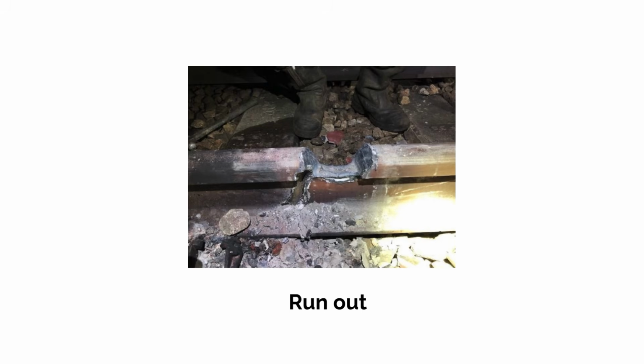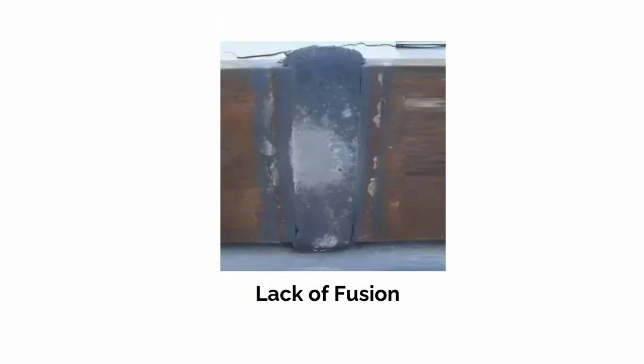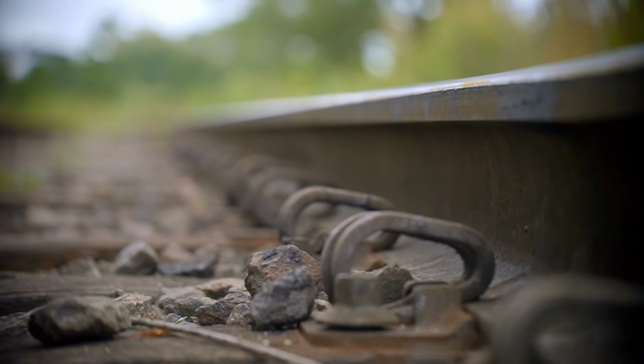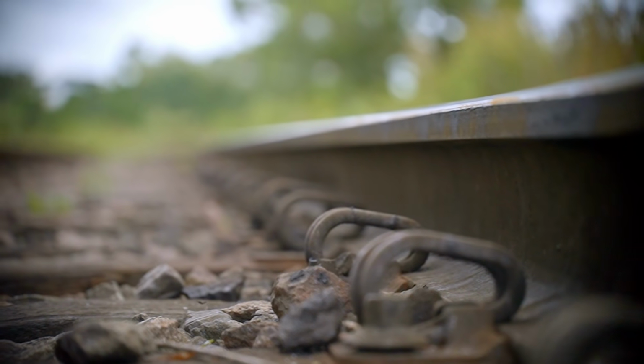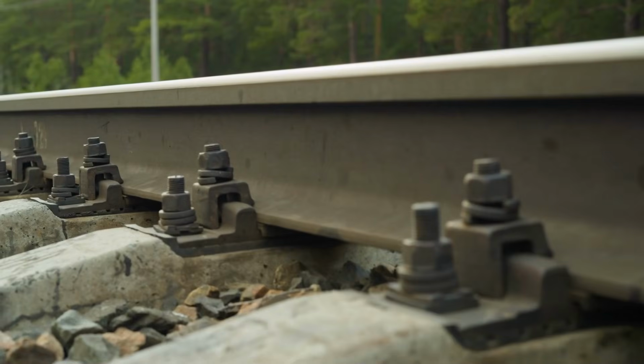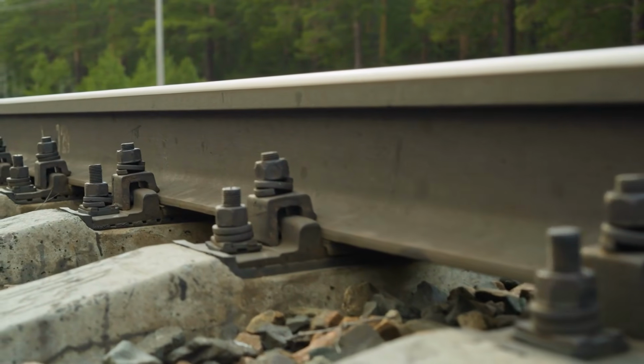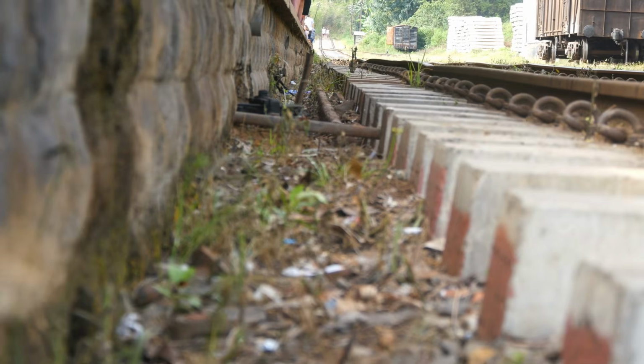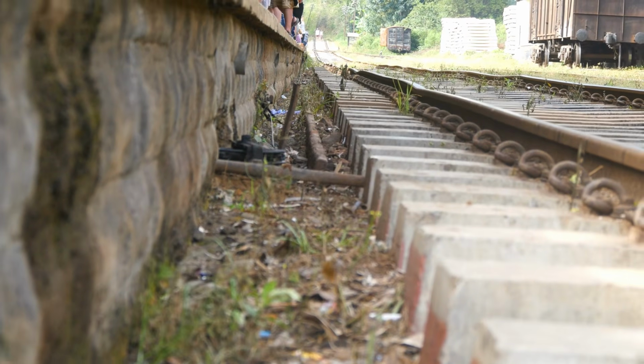A good, solid weld requires the new material to fuse with the existing rail ends and be as strong as the rail material. Lack of a proper preheat can cause lack of fusion at this interface. If the thermite reaction does not perform correctly, the resulting weld material may have lower strength than specified, meaning the joint is weaker than the rails it connects from the moment it's made.